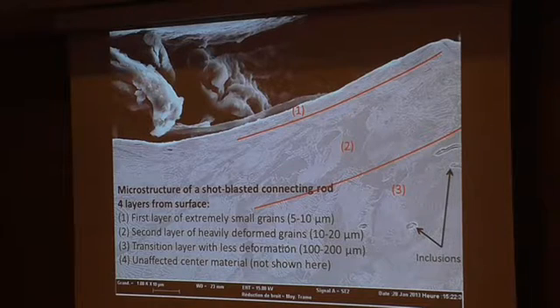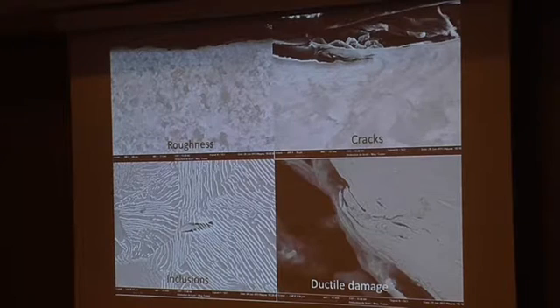Well, now when we look at what happens after forging and then shot blasting, without any fatigue, what you see here is the effect of the ball. You recognize the impact of the ball, and under this impact, usually we can distinguish 4 layers from the surface. The first layer of extremely small grains, you can see this layer here. A second layer of heavily deformed grains, the transition layer, and the original material here. And you see here on this picture, again, the impact and the gradient of microstructure.